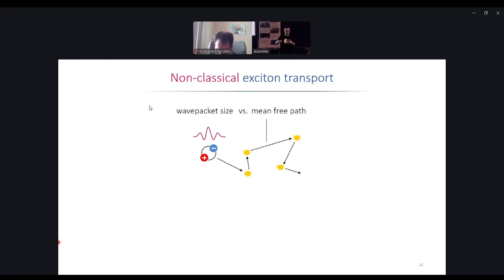The moment we have this type of picture, that we describe a quantum mechanical quasi-particle in this drift-diffusive motion, what we usually implicitly assume, and this is the so-called Mott-Ioffe-Regel criterion, is that if I am a quasi-particle, if I am an exciton, my mean free path needs to be equal to or larger than the size of my wave packet. This is the de Broglie wavelength that determines the average size of the quasi-particle.